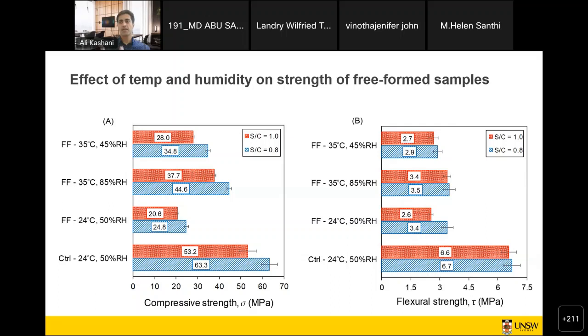And if we take out the sample, and this is something that happens in the 3D printing environment, and depends on the temperature, humidity, and wind conditions, etc. In some of those 3D printing projects on site, the mortar might be severely underhydrated.